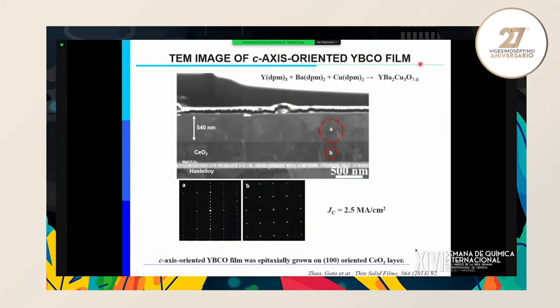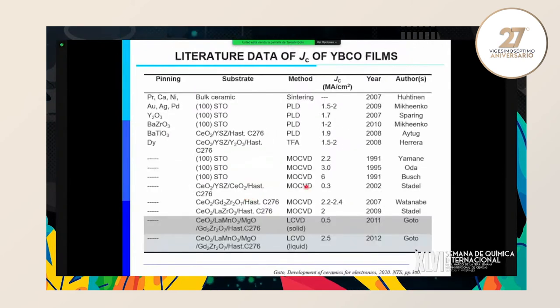And this is how the film looks. The ceria and YBCO films are well aligned and look almost single crystalline, like spots can be seen, but actually this is a mosaic structure. But we can make an almost single crystalline epitaxial film. Many people have prepared YBCO film on single crystalline strontium titanate, STO, and metal tapes, and reported critical current density, Jc. So far, our result is the highest, 2.5 megaampere per square centimeter, the best in the world.